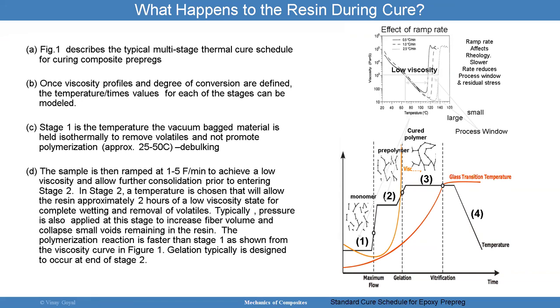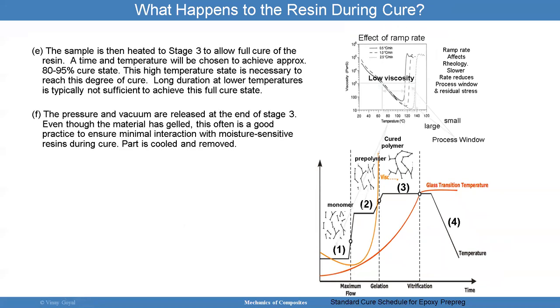This polymerization reaction is faster than is occurring in stage one. As we're showing in these viscosity plots, you know, it's kind of hard to see how this maps in here, but the gelation is usually designed to occur at the end of stage two. So over here, I'm getting some gelation already, okay? And so that's where we're getting things for real. The sample is then heated to stage three to allow full cure of the resin, right? Now we want to get there. I'm sorry, we want to get to the full cure of the resin.